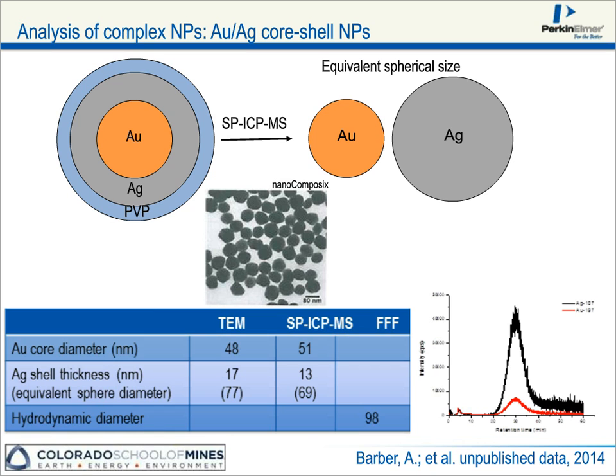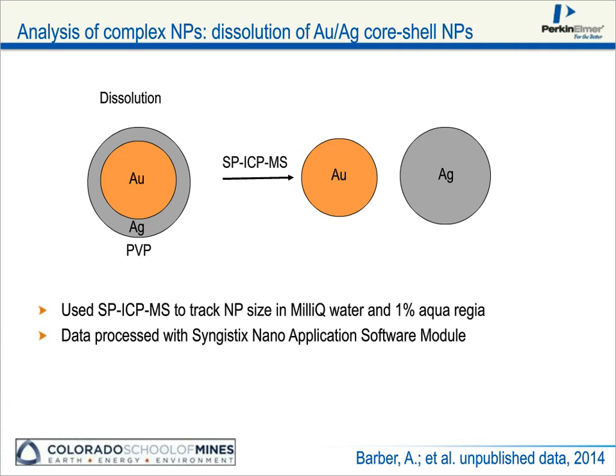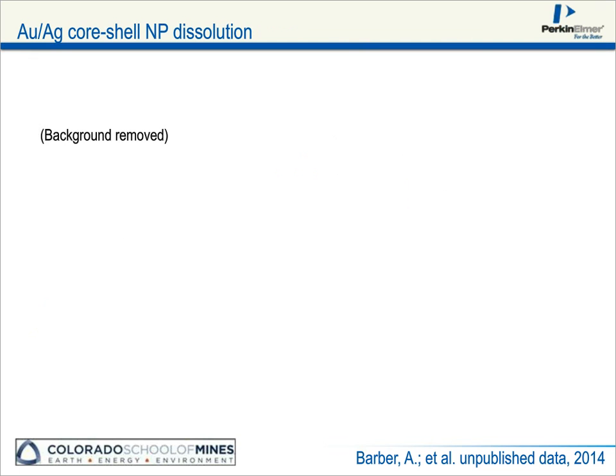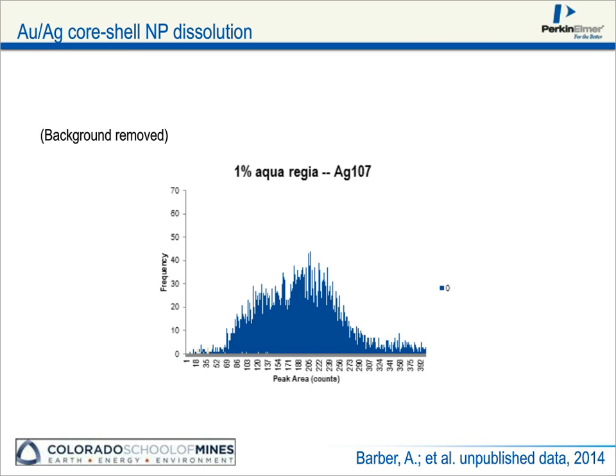And of course, I know what this particle looks like, and so I can study the dissolution of this and look at how I might be able to differentiate shell versus core. But if I didn't know what this particle was made of, then maybe this approach would also give us more information about structure. So the approach we've taken as a proof of concept is to suspend these particles in milli-Q water and 1% aqua regia, collect the data with the Syngistix Nano Application Software Module, and track the changes in these particles to, again, get at structure. If we go to the next slide, what I've got is a series of slides that show what the intensity distributions of these particles look like with time. So when we first prepare the particle, this is our silver distribution centered around 200 counts or so.